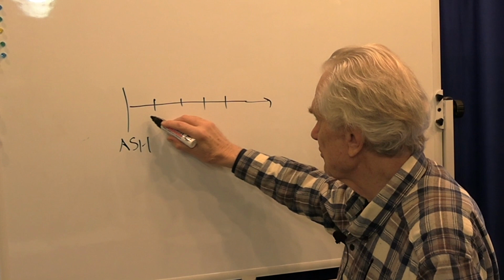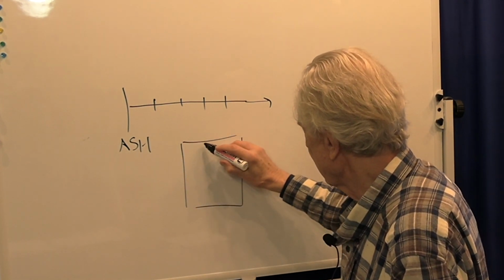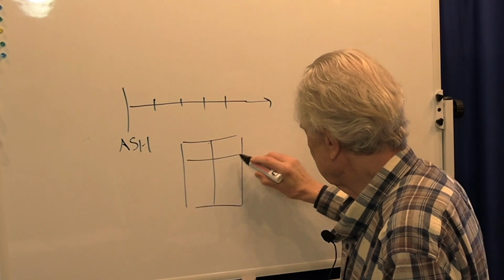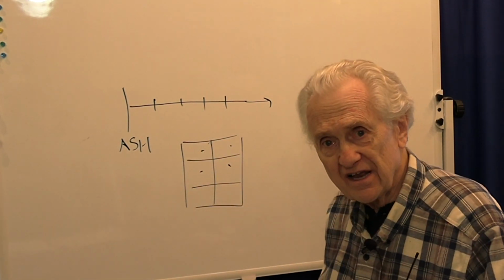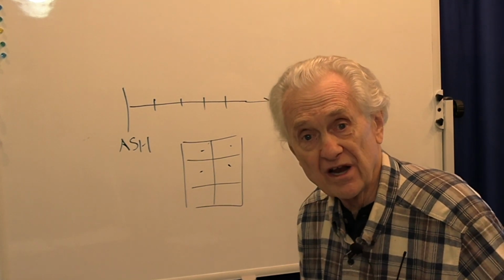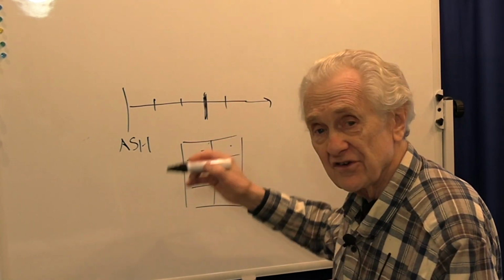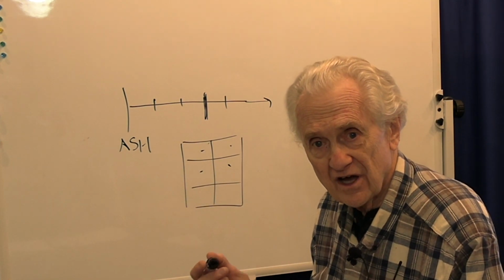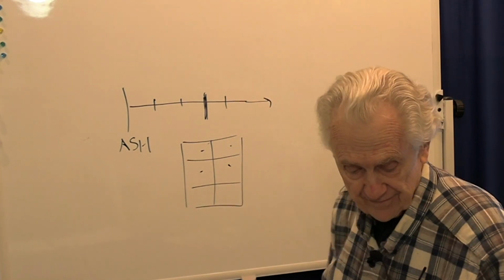And so you can do this in very small amounts. What I've done sometimes is I'll just take a clay tile and break it up and put each one of these samples in an area on the tile and fire it, cone 6 or cone 10, whatever you're shooting for, and see what composition you need to actually melt and give you a good-looking glaze at your particular temperature. This is an easy way to start, okay?